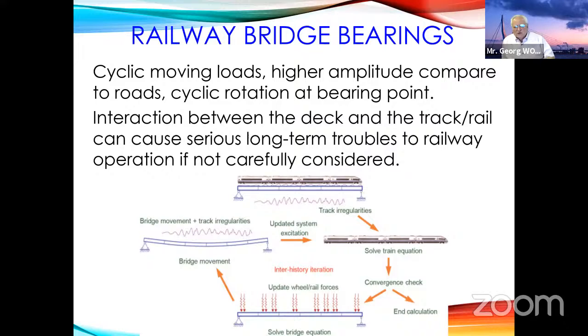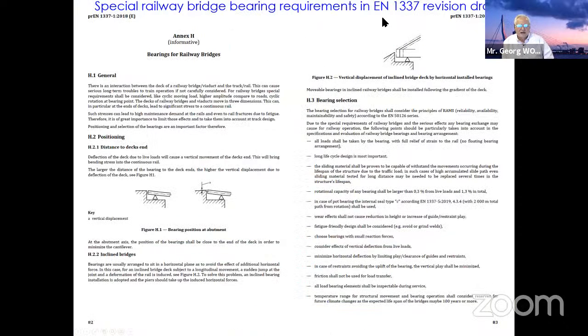There is a big interaction between the deck and the track. You always have to imagine the rail has to go through and is connected with the deck. And that's not the same in the road bridge. You have the expansion joints, and if it's a little bit bumpy there, it's not so bad. But if you have problems with the rotation of the railway bridge, then you bring a lot of additional stress to the rails, and that can make big problems. So up to now in the standards, we don't find any hints for railway bridges, but in the next revision of the European standard EN 1337, there will be an informative annex which describes in detail what you have to take care of when you select the bearing design for the railway bridge.